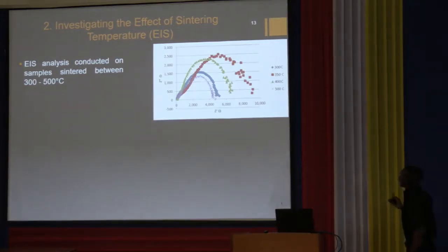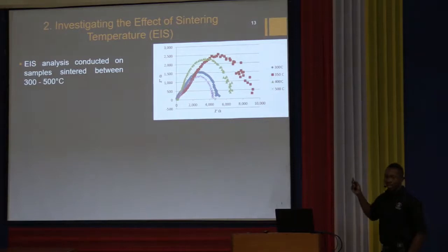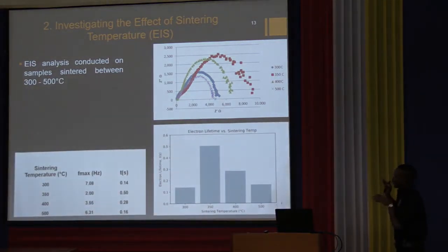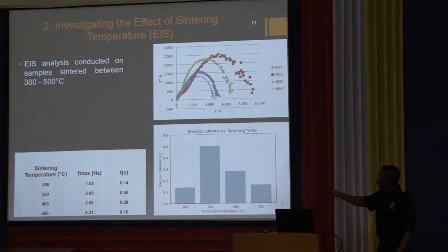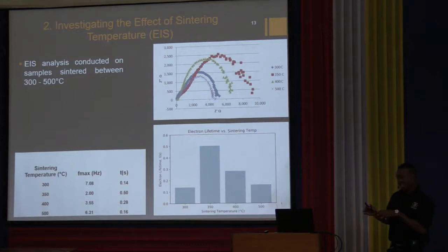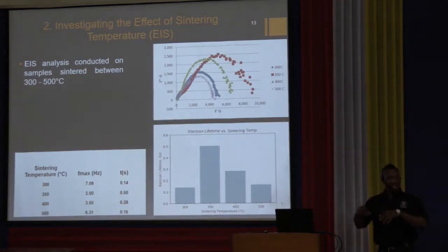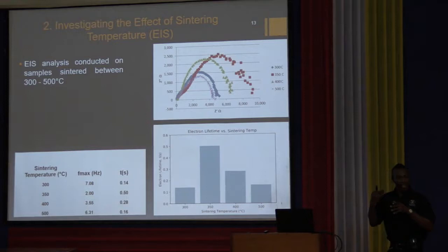The plots that we got for cells sintered between 300 degrees and 500 degrees look like this. And if you summarize this in a table, what these plots tell you is that the electron lifetime, plotted in this histogram, is greatest for cells that are sintered between 350 degrees and 400 degrees. Remember, we said that 400 gave us the best overall performance. Here, this is saying that electrons can travel through the cell for a longer period of time if it's sintered at 350.